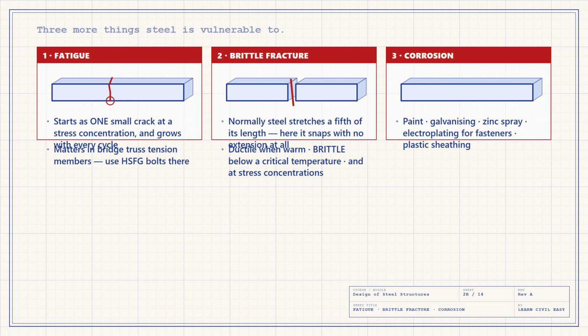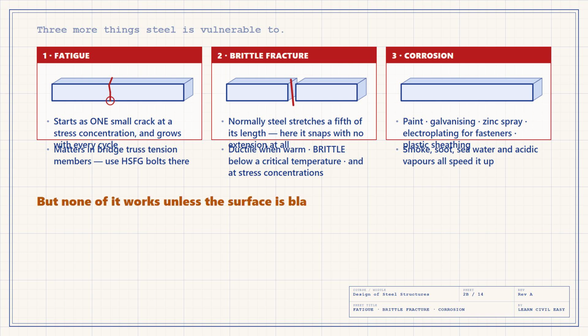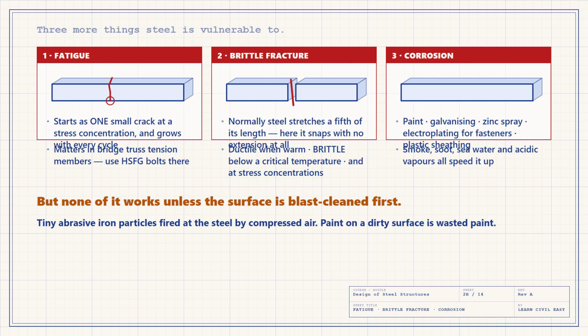And corrosion: unprotected steel rusts readily and smoke, soot, seawater, and acidic or alkaline vapors all speed it up. We protect it with paint, with metal coatings like galvanizing and zinc spraying, with aluminium or zinc metal spray, with electroplating for small items like fasteners, or with a plastic sheathing. But here is the part that decides whether any of it works. The surface must be cleaned thoroughly first. For structural steelwork, that means blast cleaning: tiny abrasive iron particles fired at the steel by compressed air. Paint on a dirty surface is wasted paint. The bond is the protection.